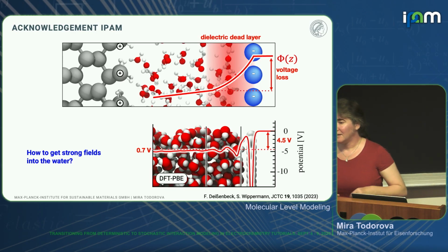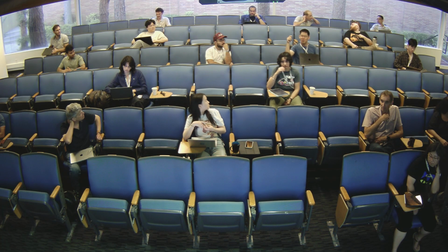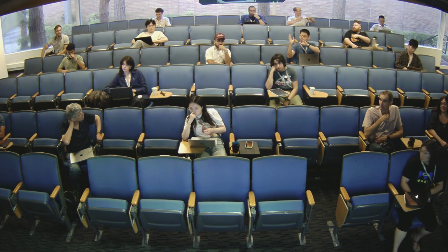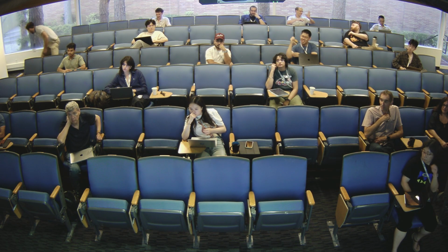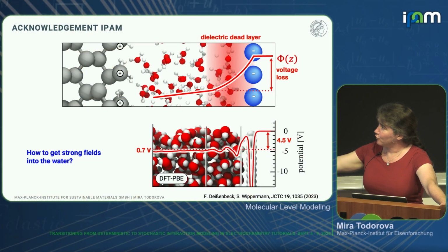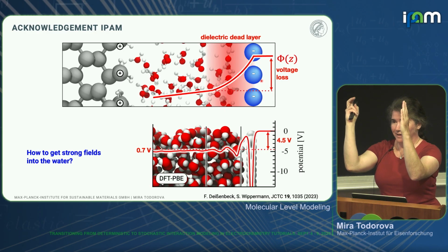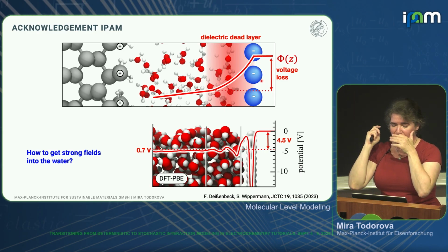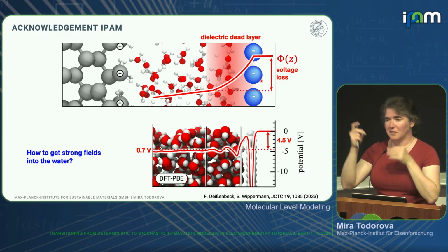Yes. Thank you. This might be a naive question. So I wonder, what is the mechanism for this drop? Is it because near the boundary, the orientation of the water is restricted by the boundary, or something else? No, the drop is actually really due to us having here a hydrophobic gap. So there is a little bit, let's say, space between the ion and the water, and this is like having a vacuum region.